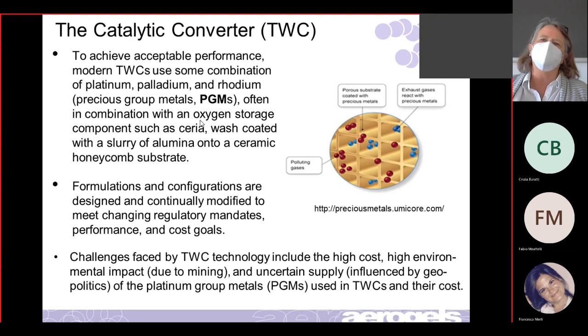And it's all wash coated, is the phrasing, wash coated with a slurry, which is a mix of alumina, onto the substrate. And so, here's showing in red the polluting gases. And then here's the substrate, which creates a reaction. And now we have the blue, which is the better stuff coming out.